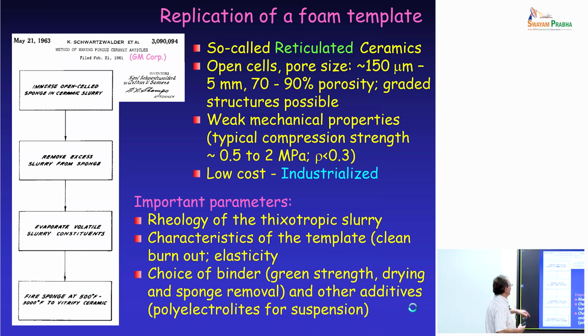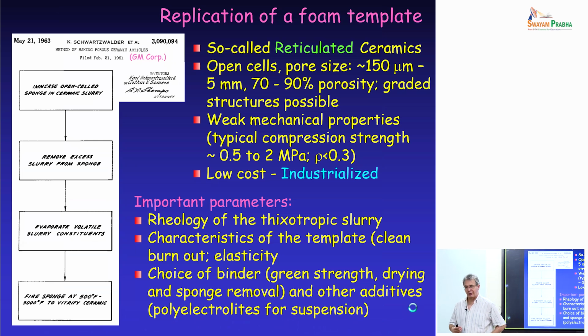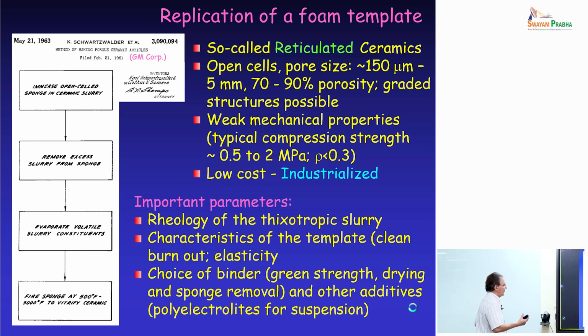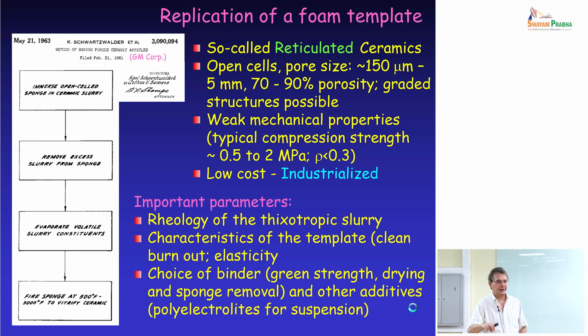And if you look at the patent, it was issued in 1963, but the interesting point is that it was issued to a guy working for GM, the car manufacturer, because the foams, ceramic foams, reticulated ceramic foams were used as catalyst support for cars. And this technology is very simple. You have a slurry with your ceramic material. You have a polymeric sponge with open cells, and you simply immerse the polymeric foam into the suspension. Then you lift it, and the slurry has coated your polymeric foam, and then you sinter.